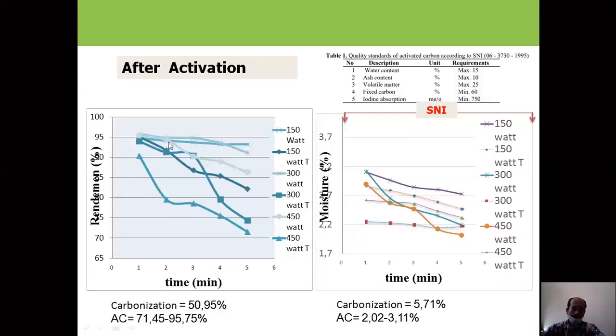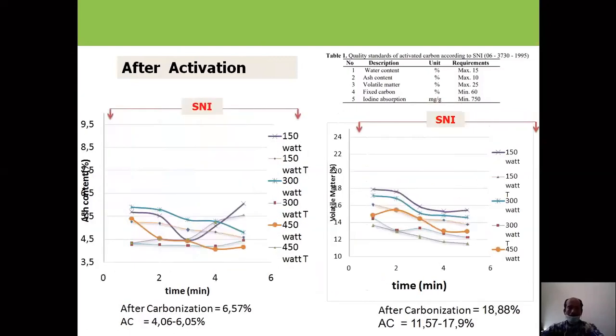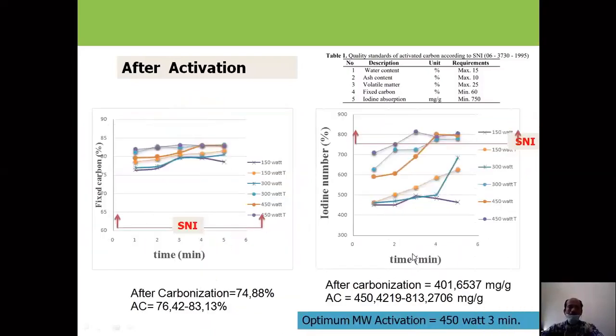This is our sample after activation. This is the rendement. The content of water is still under the required maximum number of SNI, so it's okay. And all of the values for ash content are also under the required maximum number of SNI, so it is good. The volatile matter is also still under the required maximum value of SNI, so no problem. Now for fixed carbon, all of them are good because they are more than the expected value of SNI.